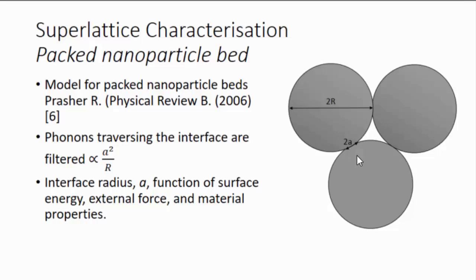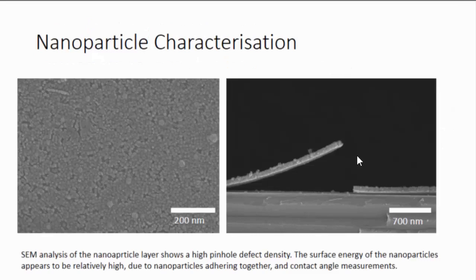And this nanoparticle radius here is not actually simply a function of geometry. It is also a function of the surface energy of the nanoparticles and also the external force put upon it. In our bed, because we're not putting any external force upon it, it essentially becomes just a function of the nanoparticle surface energy. So this is a little bit of analysis of our nanoparticles and essentially trying to adapt what we found in this existing model to our system.